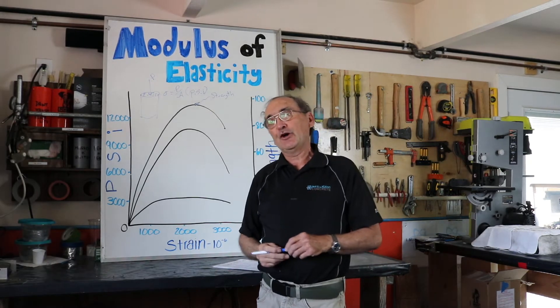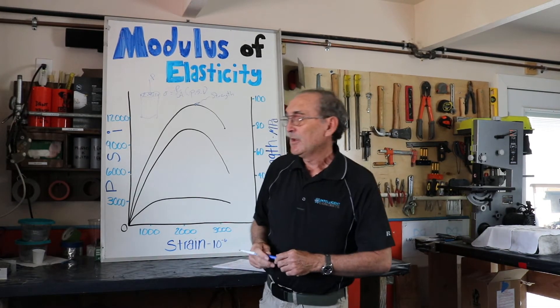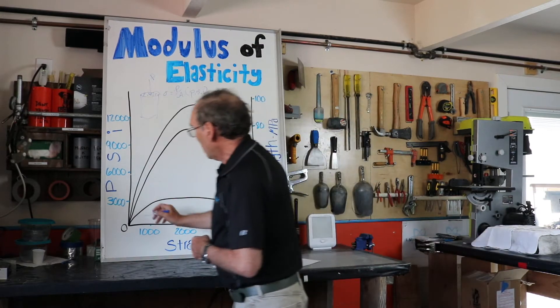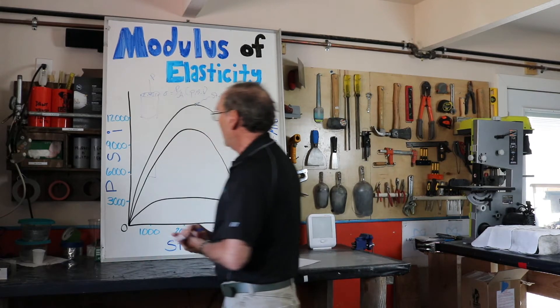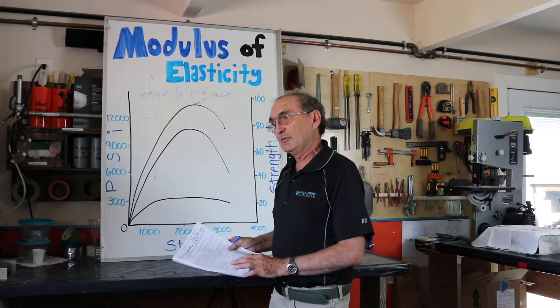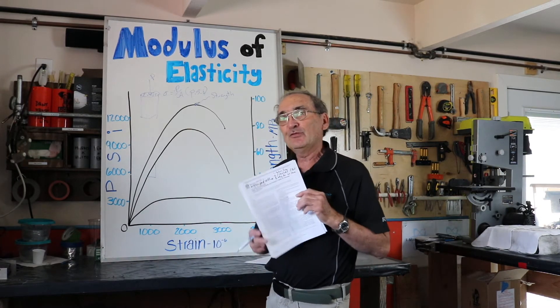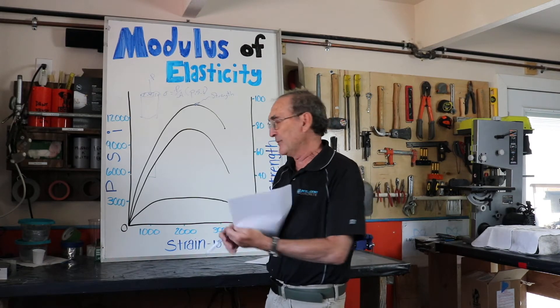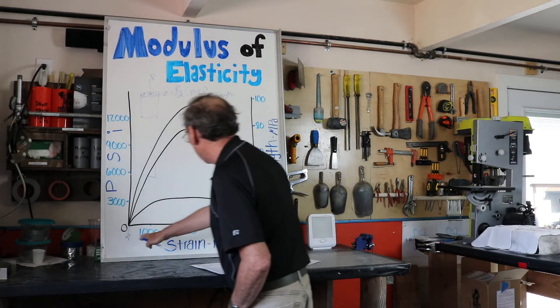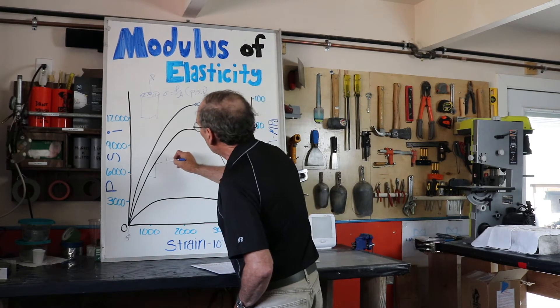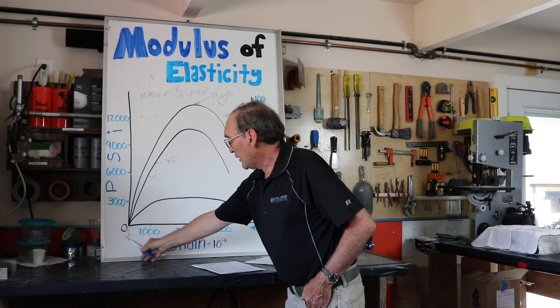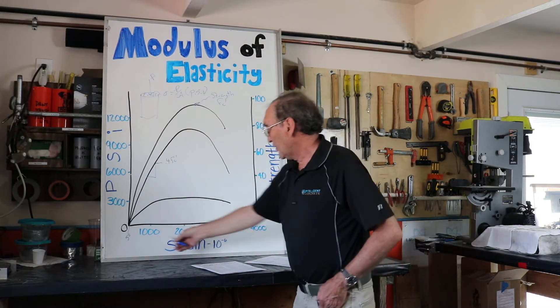Now let's talk about today's topic: the modulus of elasticity. Modulus of elasticity is found from the stress-strain data — we take the slope of the stress-strain curve. If we refer to ASTM C469, which is the Bible for testing, they tell us to calculate from 50 microstrain up to 0.4 FC prime. This is strain on this axis.